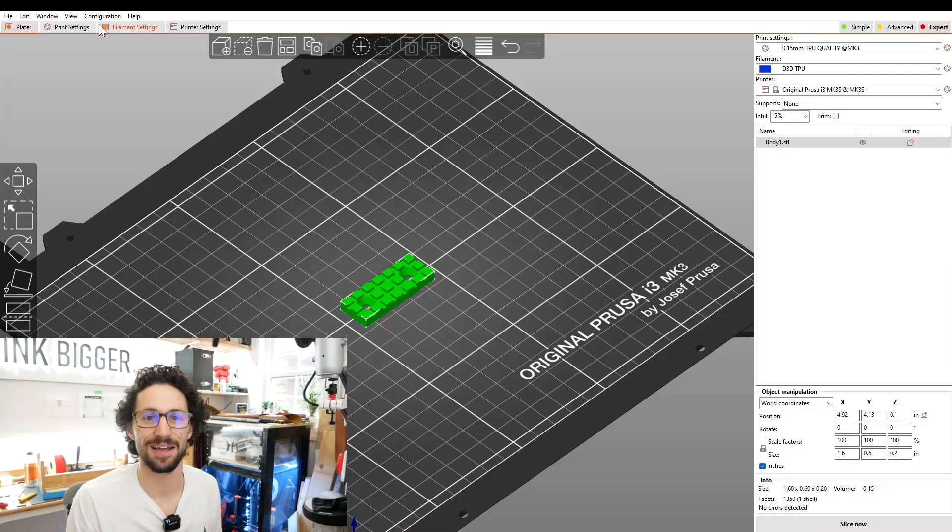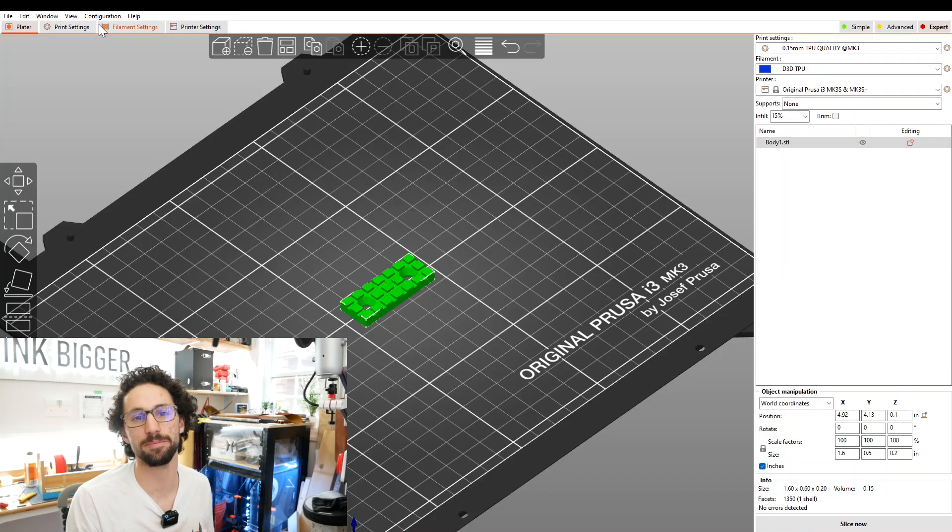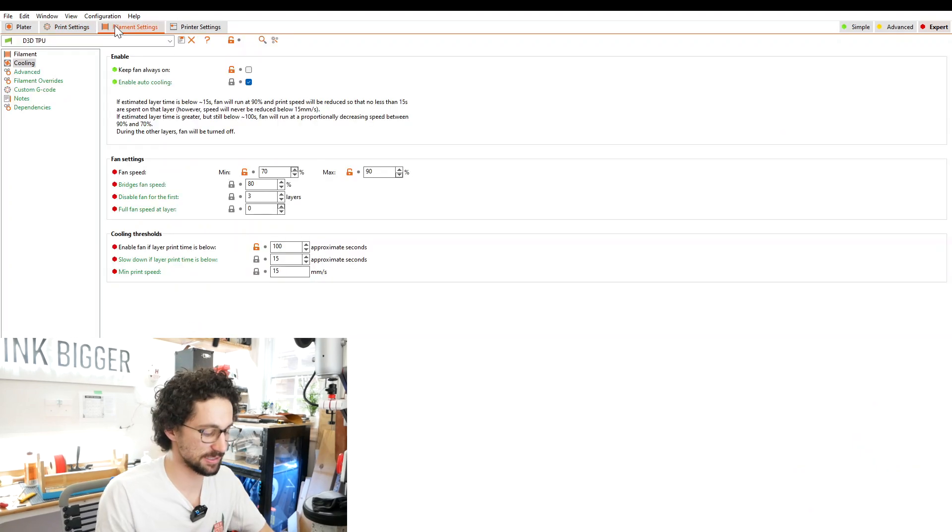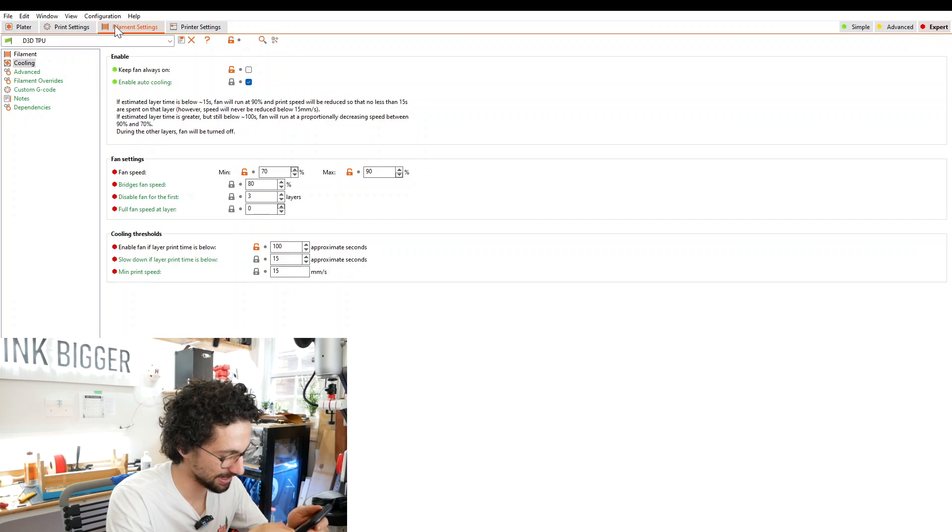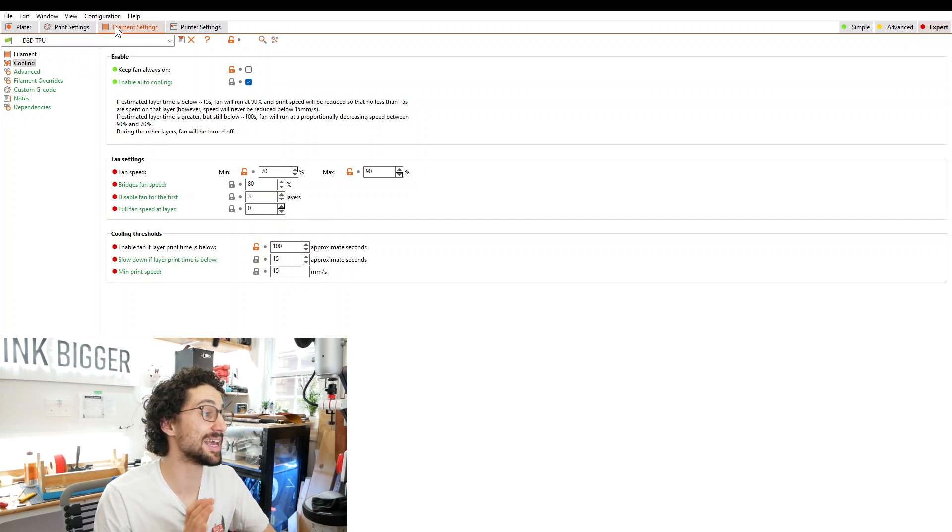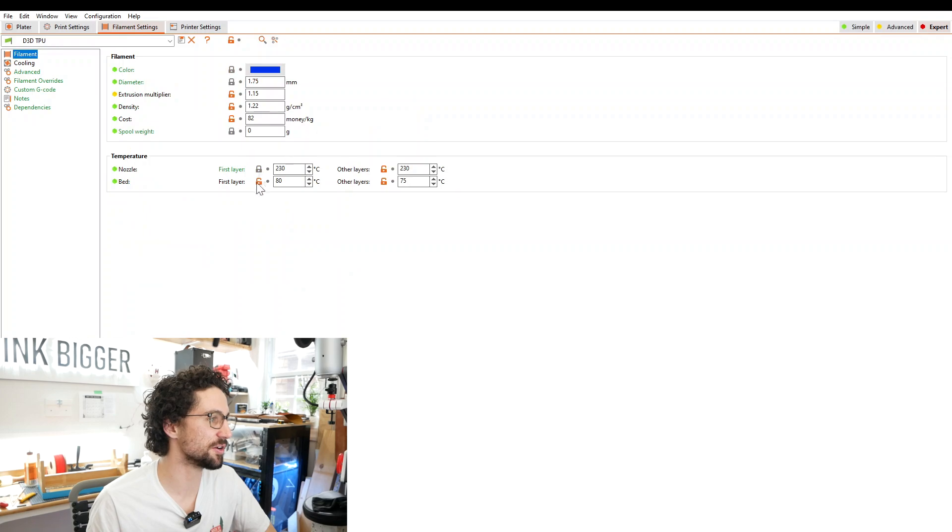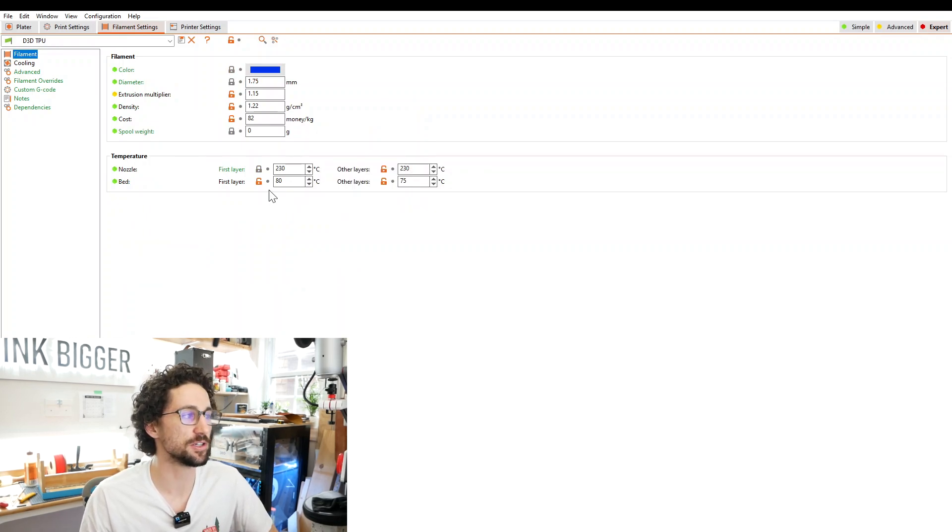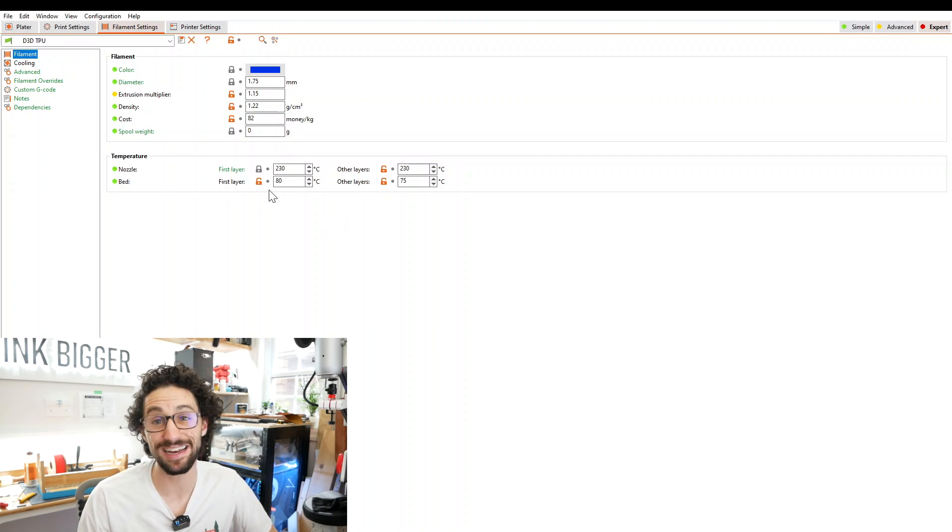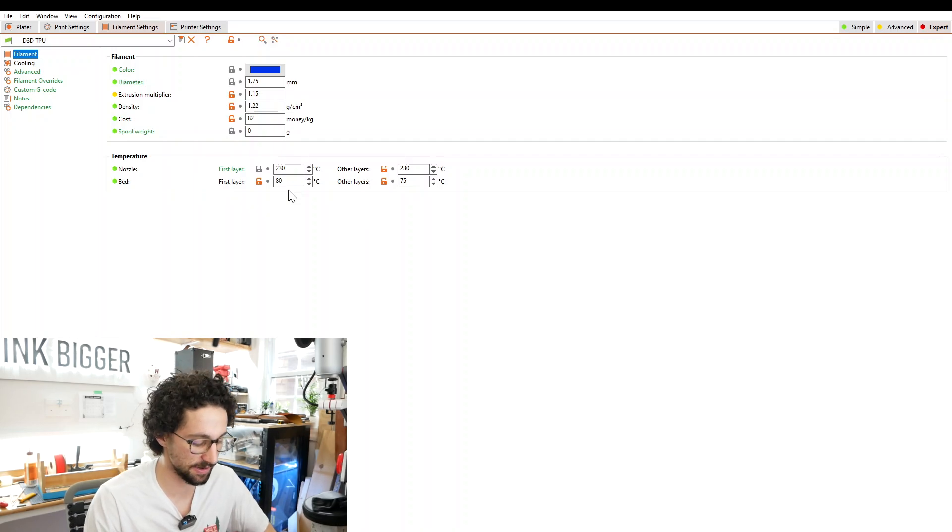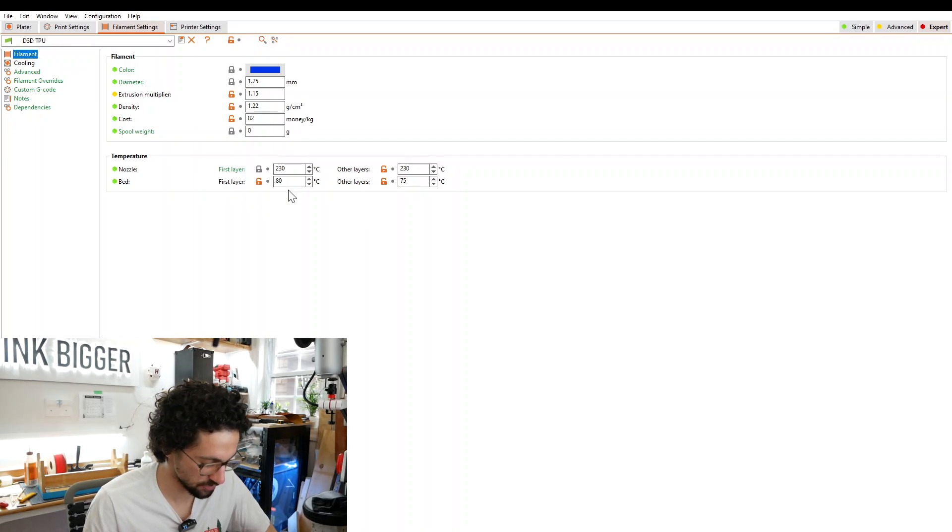One of my good friends who has the exact same printer as I do got some TPU and he used it successfully. So I got his print settings, used that as a starting point, and it really demystified the whole process. I'm going to show you my print settings - hopefully it will tell you a little bit about why you use the settings that you do. But my number one suggestion is to find a friend who has the same printer, find someone on the internet even, and use their print settings as a starting point. I used a TPU filament profile in PrusaSlicer as a starting point and then used my friend's filament settings to tweak it. First thing is the temperature, most important. Let's go to Filament - I'm printing this at 230 degrees Celsius. First layer bed temperature is 80 degrees, subsequent layer bed temperature is 75 degrees.